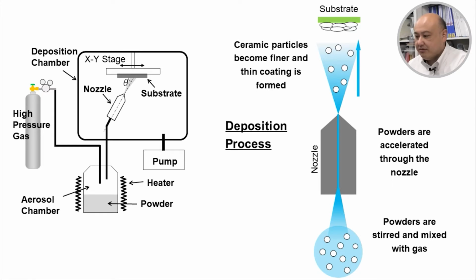And in addition, this material must be protected from the external environment. So this is a related point. In our laboratory, we are investigating aerosol deposition, which I will call the AD method later, which can produce ceramic coating at room temperature, where the material will not be damaged from the substrate.